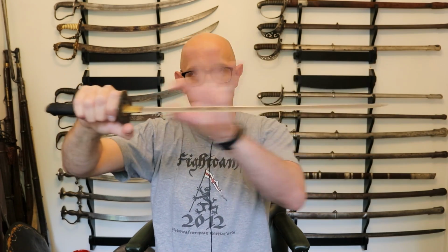And indeed, I'm certainly not going to do it with this lovely antique, but if I took the blade by the other end and bent it as hard as I could, it would bend and stay bent. But because it's a thick blade, it's less likely to do that than some of the thinner European or even Chinese blades, or even in some cases Indian blades as well. So it's a thick blade, not particularly broad, you'll notice. They've taken the same amount of material and built it up in the thickness of the blade so that it's more resilient to bending, but a very hard edge. As a typical comparison, a medieval European sword blade might be around 40-45 Rockwell at the edge. That's a hardness measure, whereas a Japanese sword might be 60 Rockwell at the edge. So these are significantly harder at the edge.